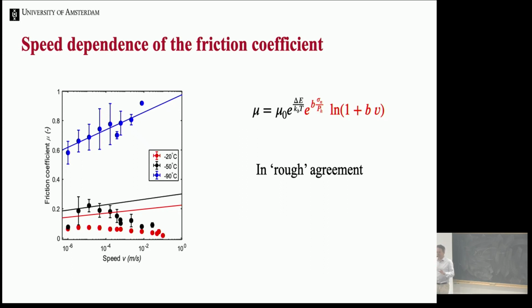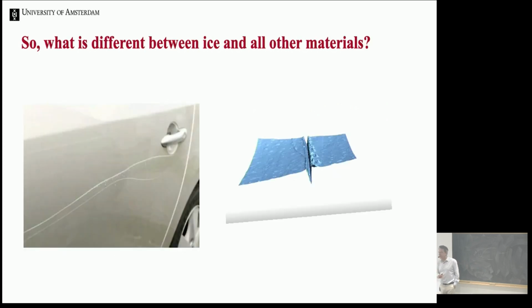And so this was my remark about roughness is always complicated because roughness is always a power law behavior in the length scale. So this is really a big mess because in order to fully characterize your surfaces, you need to measure all scales. Anyways, we now understand friction, so I want to conclude this part with trying to convince you that there's something very easy that is different between ice and all other materials, and that's of course the mobility of the molecules at the surface.